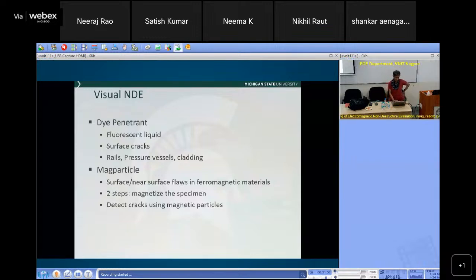Okay, so it takes fluorescent liquid, which goes into the surface cracks, but they were used in rails and pressure vessels in the power plants. The cladding in the pressure vessels were all detected. Those cracks were detected using dye penetrant. But again, it can only do the surface cracks. And very often, cracks can be below the surface, and we'll see that later.